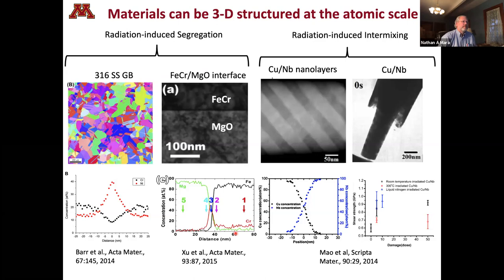The other thing you can do is you can do this stuff on purpose. If we take our copper niobium, one of our favorite materials, and we ion irradiate this, you can start to blur these interfaces from the ballistic collisions that happen between an incoming ion and your material. What that does is it can induce a certain amount of mixing. So at the interface, you can have a copper concentration gradient and a niobium concentration gradient that occurs over about 20 nanometers or so, depending on your irradiation conditions. What does that do to our mechanical properties?